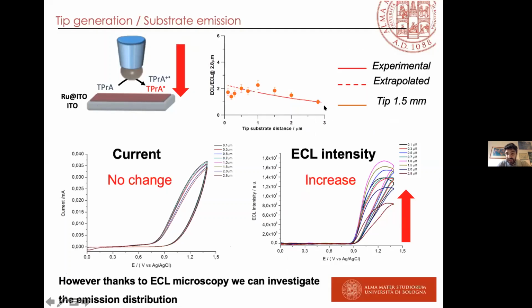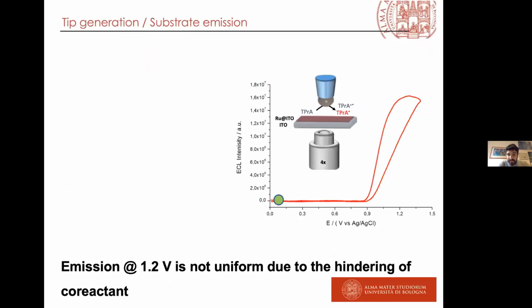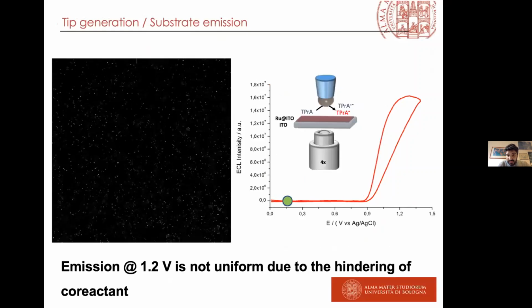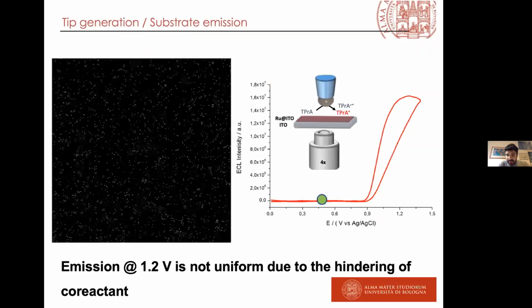And we have an increase, and these are our orange dots. You see that we have an increase that is very similar to the red curve, the experiment obtained by Bard and co-workers. So the orange dot is our experiment, and the red one is the Bard one. But this is the movie that we obtain by increasing the potential.